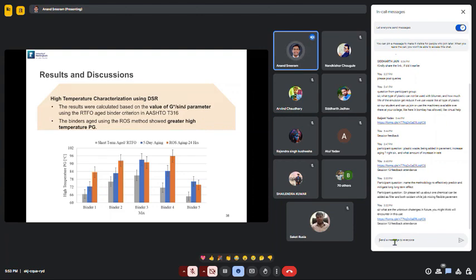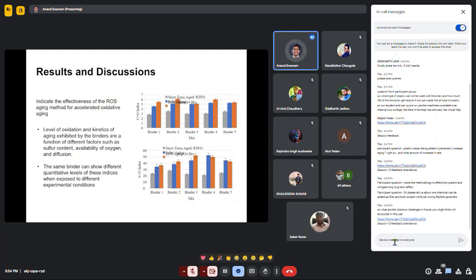After the aging process, we recovered the binders using solvent extraction, and then we characterized them for rheology using a dynamic shear rheometer. These results were calculated based on some very basic parameters such as the G star sine delta parameter. We could see that the binders aged using the ozone method showed higher PG grade, meaning they were more stiff and actually more aged, right? So this showed the effectiveness of this method to accelerate oxidative aging.